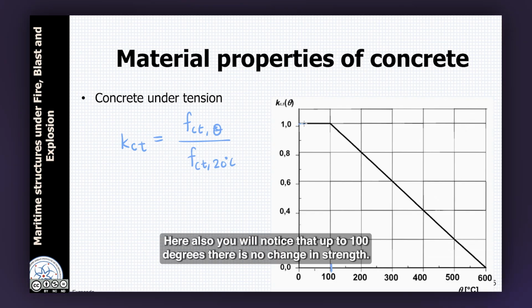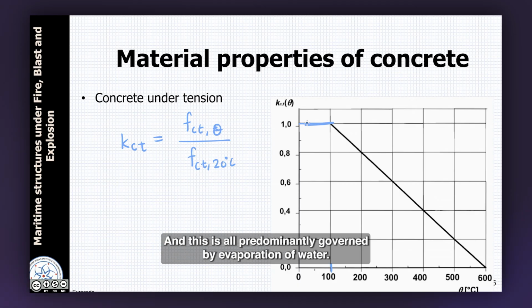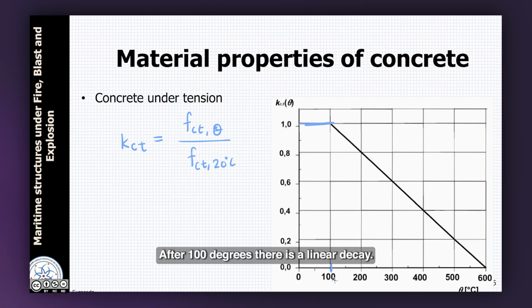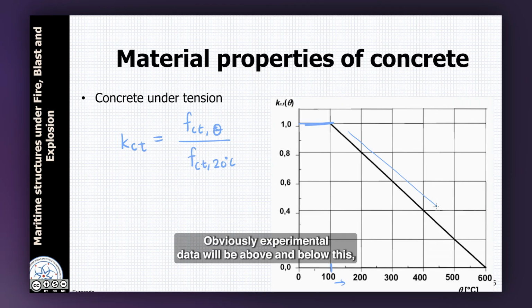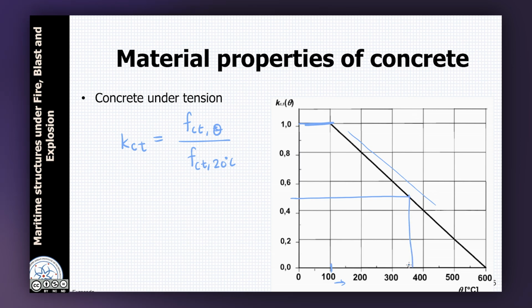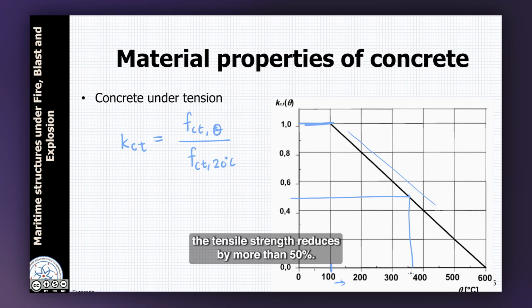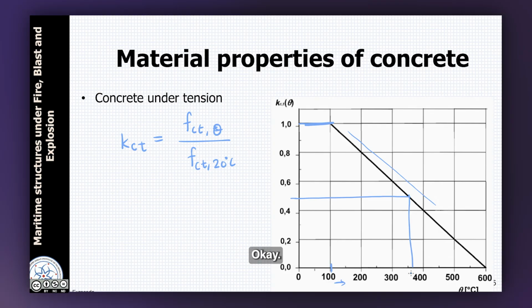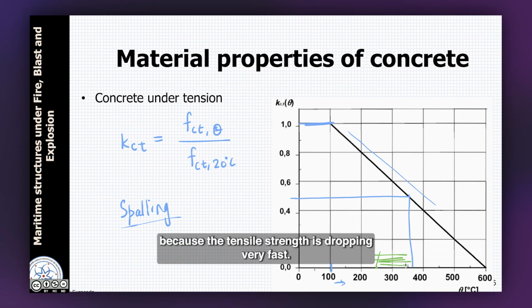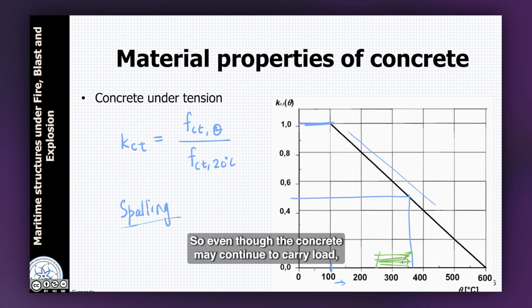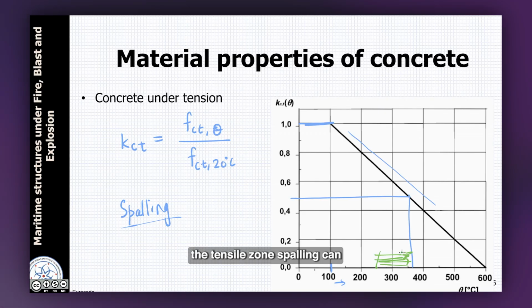Okay, here also you will notice that up to 100 degrees there is no change in strength, and this is all predominantly governed by evaporation of water. After 100 degrees there is a linear decay. Okay. Obviously experimental data will be above and below this, but this is a general regression line. Okay. And if we were to draw a line at 50, which is 50% of the strength, we will see that around less than 400 degrees, the tensile strength reduces by more than 50%. Okay. So for this reason, spalling can initiate even in the early stages of temperature exposure, okay, because the tensile strength is dropping very fast. Okay. So even though the concrete may continue to carry load, the tensile zone spalling can begin much before 400 degrees Celsius.